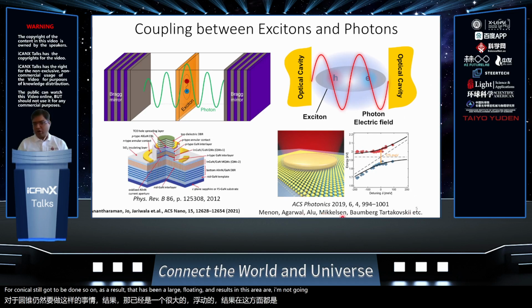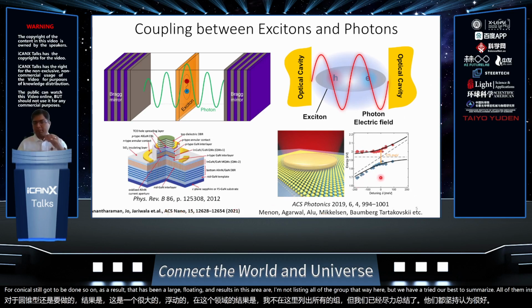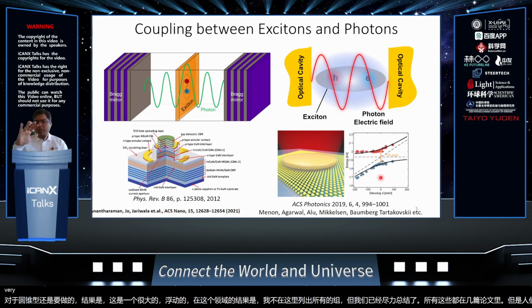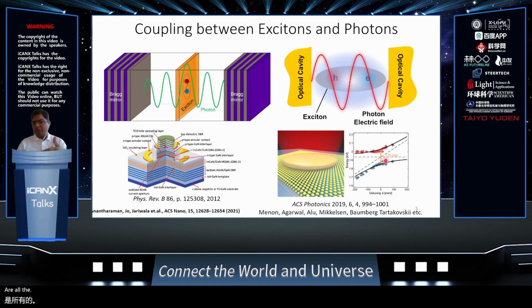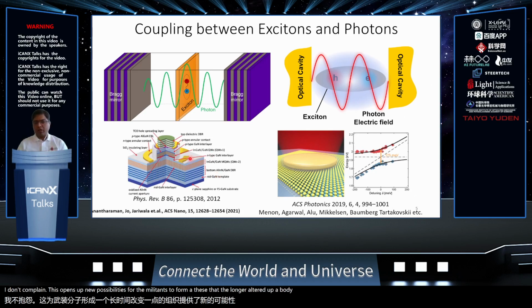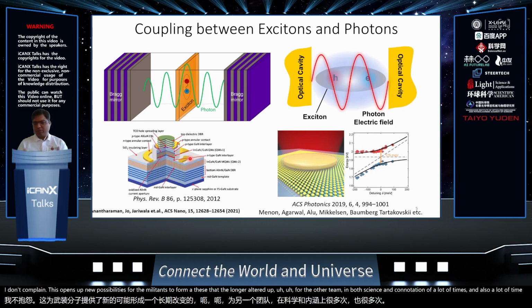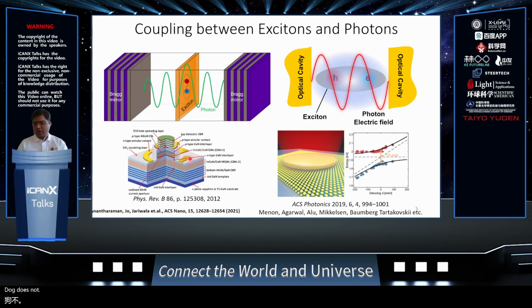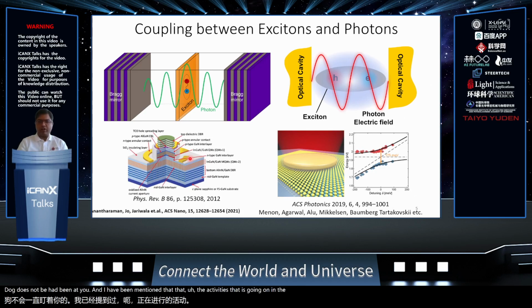I'm not listing all of the groups here, but we have tried our best to summarize all of them in this review paper. But people have been able to see very large Rabi splittings of more than 100 meV, or even a couple hundred meV, at room temperature. This opens up new possibilities to achieve the long-heralded Bose-Einstein condensation of polaritons and also polariton lasers at room temperature, though that has not yet been achieved. And I should mention that active research is going on in this area by many groups.